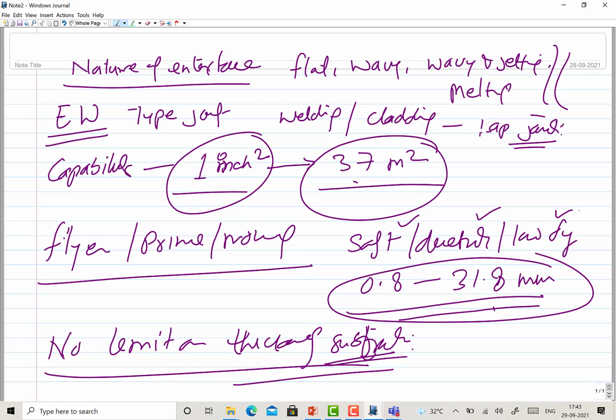Say for example, if you use a very high strength and brittle metal having ductility of just 2%, or the toughness is very limited, say 5 joule, then you will find that under the impact conditions from the explosive, the prime component itself is getting cracked.